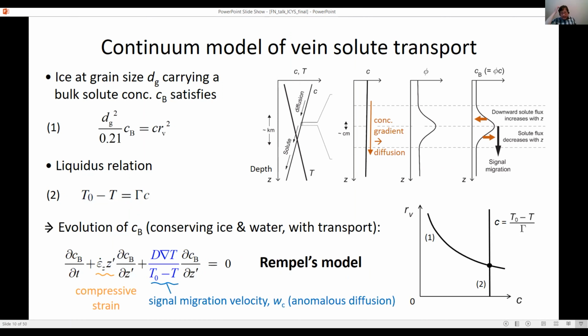So when we formulate all these ingredients into a continuum model, you get this differential equation, which is their model. Obviously, at ice core sites, the signal is going to be narrowed under compression, but then we get this additional migration of the signal against the ice. And I've highlighted the migration velocity in blue here. It's faster when warmer.